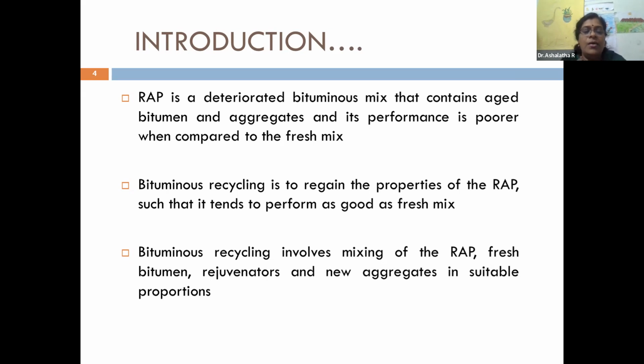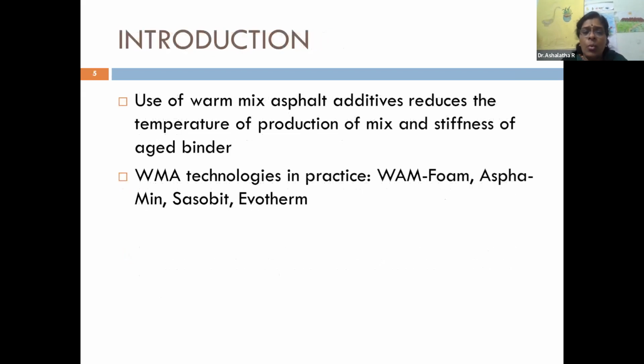Okay, so it involves mixing of the RAP, fresh bitumen, rejuvenators, and new aggregates in suitable proportion. So what is that proportion? That is what we were exploring in our first work. And later on, we tried to use warm mix asphalt additives, because it is known that warm mix asphalt additives reduce the temperature of production of mix and stiffness of the aged binder. And warm mix asphalt technologies in practice include WAM-Foam, Aspha-Min, Sasobit, Evotherm.